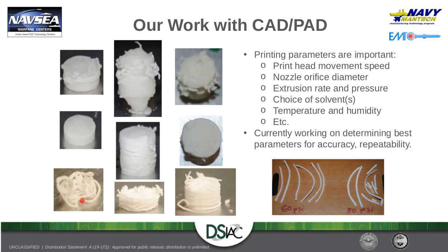The nozzle orifice diameter dictates the available resolution that you have in X, Y, and Z, so it especially affects your ability to print very fine features. If your nozzle's too big, you're not going to be printing very fine details. And if your nozzle's too small, then you are able to print all those very fine features, but it takes a very, very, very long time. So it's an important parameter.